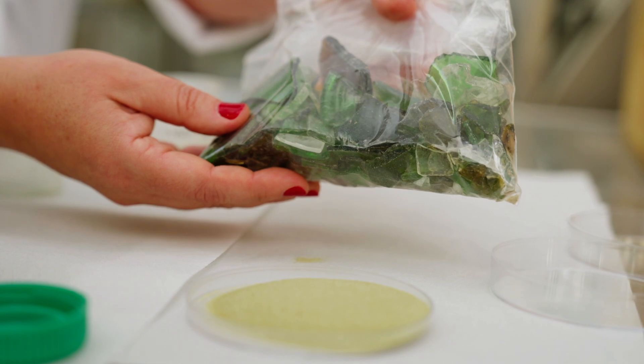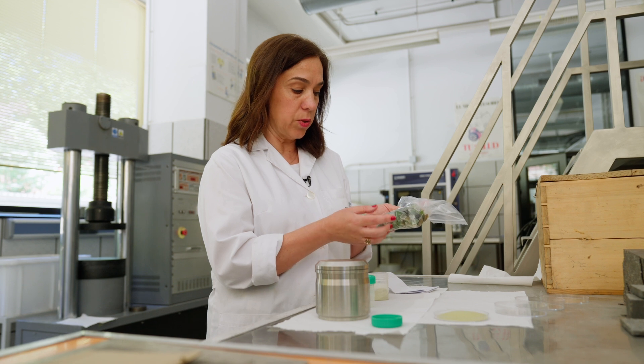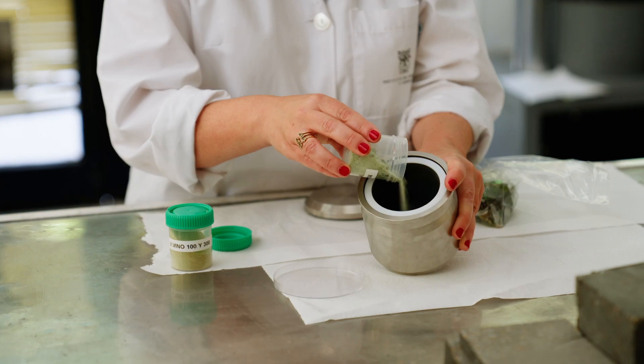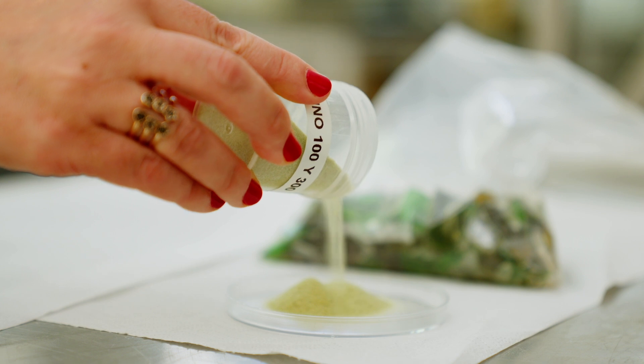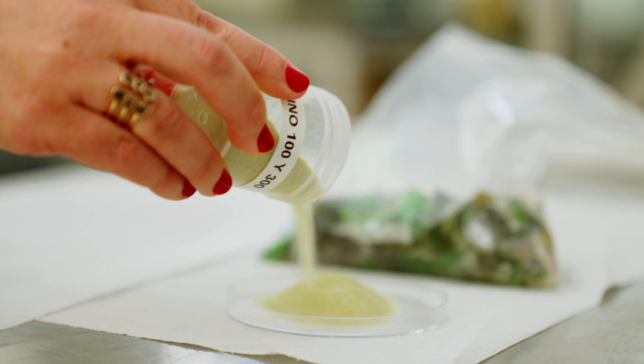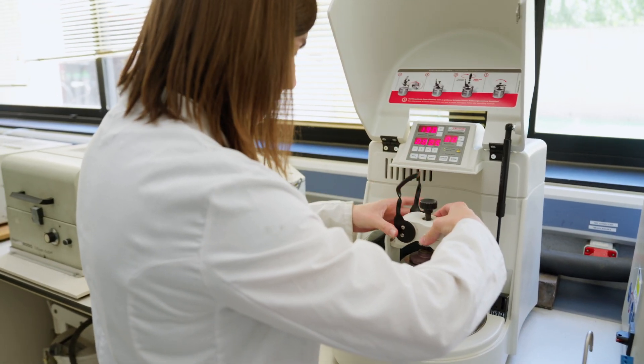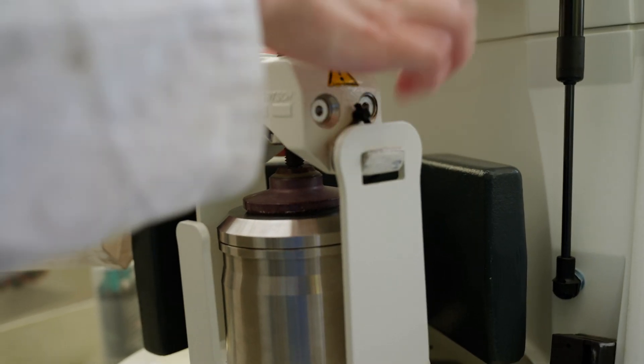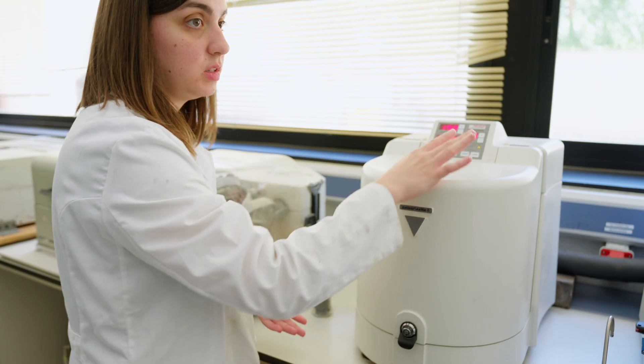This is a typical waste that we can receive — in this case, a mixture of glass container bottles of different colours. When I prepare samples for the laser processing, I need to do all the conditioning from this glass waste to get a glass powder that has the right particle size and characteristics to be fed into the laser melting machine. So what we are going to do now is crush the glass a little bit finer and introduce it in a mill to get finer powders that are suitable for the laser melting process.